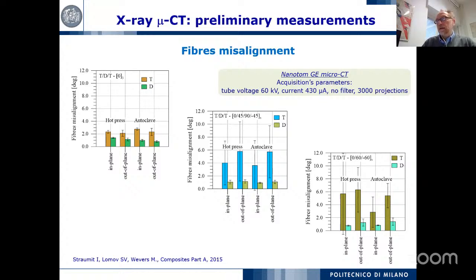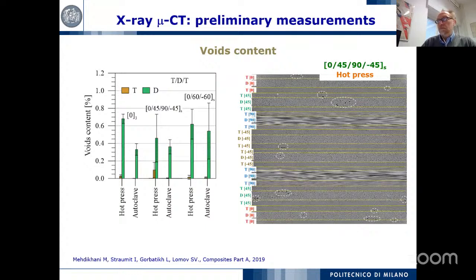On the other hand, if you look at the void contents that have been measured with images from micro CT, the void content that is quite reasonable for many applications is mainly in the low elongation ply, the carbon ply. And this is also not so different comparing hot press and autoclave. So from this aspect, the two manufacturing techniques give almost the same quality of the material.